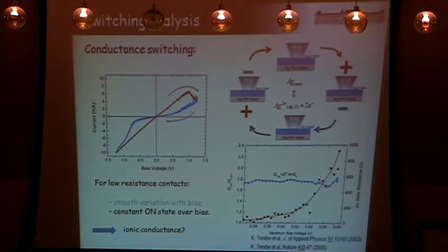Sometimes in the literature, these are just two examples, they have the argument that metallic silver can dissolve back and forth in a silver sulfide surface. For our case, we didn't put any silver sulfide on purpose. So I have to stress that most likely this is some sort of surface contamination. And indeed, Rutherford scattering data showed later on that we indeed had sulfur on the surface, although we didn't really have much data on the profile.